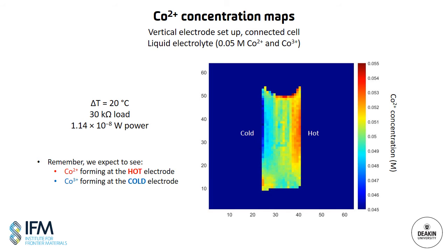So this is a cobalt 2+ concentration map obtained from a liquid electrolyte in the vertical electrode cell. The electrolyte contains 0.05 molar concentrations of both redox species. And the temperature difference between the two electrodes in this case is only 20 degrees C.